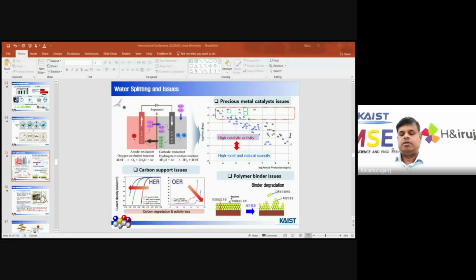When we buy the commercial platinum carbon or iridium oxide or ruthenium oxide, we need to use some binders. When we use the binder, we have to use some acidic or basic media, even seawater, which is a highly corrosive media. The polymer binder slowly degrades. So after a few cycles, for example, we need to get a lower potential for OER, and a lower potential for HER, hydrogen evolution. But you see, after a few cycles, the potential increased drastically. In the case of OER also, a drastic increment happened after 22 cycles because of this polymer degradation.